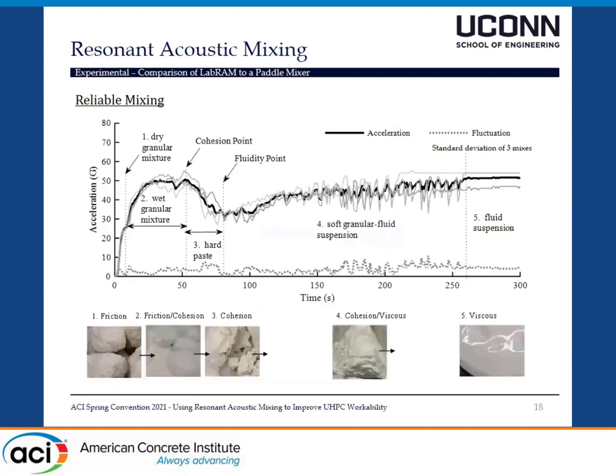Okay. Does it give reliable mixing? In terms of providing the same mixing results each time, what we see in this picture is the average acceleration between 3 different mixes at the same intensity. Through the clear container, we can see the different stages of mixing: the frictional stage, the friction to cohesion stage, cohesion, and then finally the viscous stage.